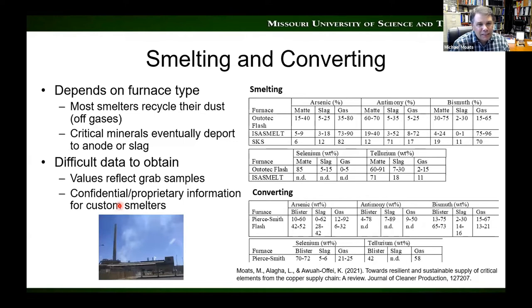In copper smelting, there's at least 6 or 7 different types of furnaces that do the smelting. And as such, the deportment of elements coming out of those primary smelters can be dramatic. So we have here the Outotec flash furnace, the Isasmelt, which is a top-blown lance, and then the newer Chinese bottom-blowing SKS furnace. And you can see that while there's some overlap of where the arsenic, antimony, bismuth report, there's some differences. And those differences relate to the matte grade that's produced at the end, which is the copper concentration at the end, or how it's run. And so there's quite a variability here.